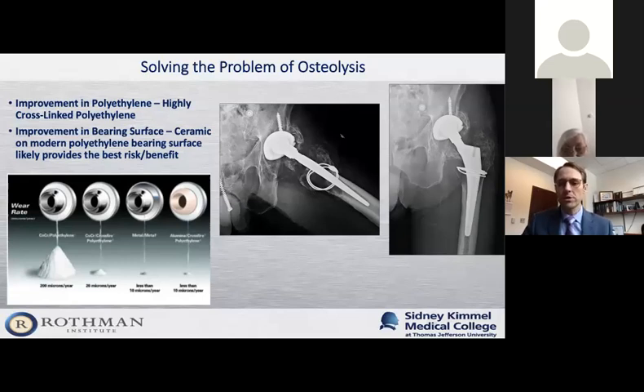Eventually, some smart engineers and orthopedic surgeons discovered that if they radiated the plastic, it caused it to become highly cross-linked, making it incredibly resistant to wear. However, it wasn't just as easy as irradiating the polyethylene to solve the problem. In fact, irradiating the polyethylene then created free radicals that caused oxidation and breakdown of the polyethylene. So a process had to be developed to help remove those free radicals that we refer to as annealing or remelting, which then gets rid of the free radicals.